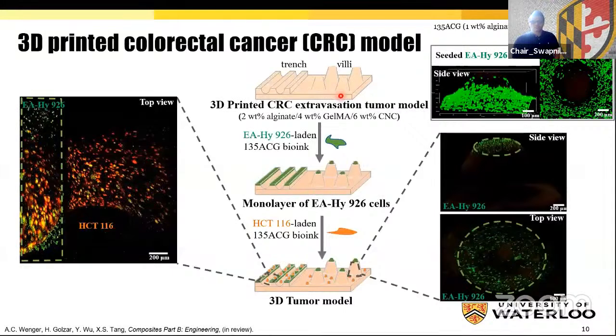To achieve an appropriate tumor model for investigating extravasation, we not only should have a monolayer of endothelial cells even on top of the villi, but also need to be able to precisely deposit cells in a well-defined pattern. However, from the fluorescent images, there were no cells attached at the top of the villi after seeding EAHY926 cells on the substrate, despite treating the printed model with poly-L-lysine.